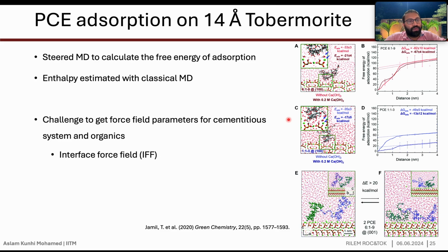This goes back to what I said earlier, that people don't use the real CSH surface because people still don't have an understanding of what the realistic or representative features on the CSH surface would be. So they were able to use steered MD to push the polymer onto the surface and see what the free energy of adsorption is. Often the difficulty with these organic-inorganic calculations is getting the force field parameters,